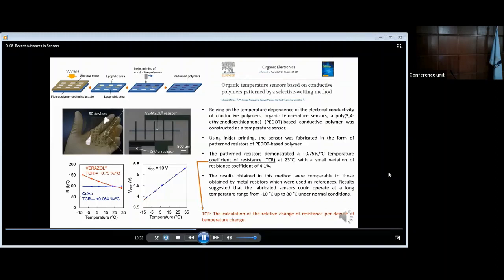These sensors show a very small variation of resistance coefficient of about 4.1%. The results in this method were comparable to those obtained by metal resistors. These metal resistors were used in this study as references to compare the performance. Results suggested that the fabricated sensors here in this study could operate at a low temperature range from minus 10 degrees Celsius up to 80 degrees under normal conditions.